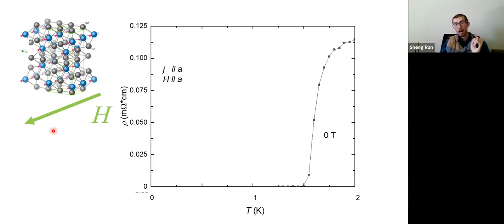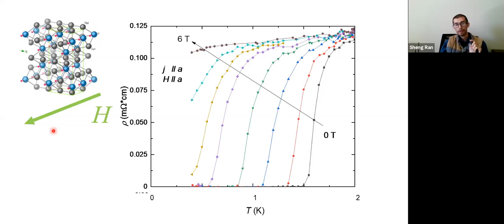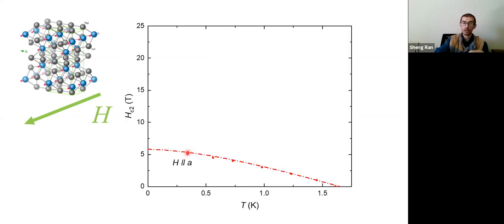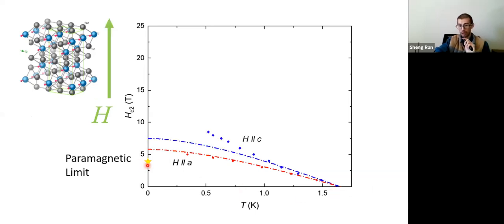If we apply the magnetic field along the a axis, this is what happened. So indeed, by 6 Tesla, we suppress the superconductivity. If we plot the critical field as a function of temperature, this follows the WHH curve very well. So indicating along this axis, really the orbital effect is dominant. And the paramagnetic limit is about 3 Tesla in this compound. Now, if we apply the magnetic field along the c-axis, you can see it starts to deviate, but not too much.